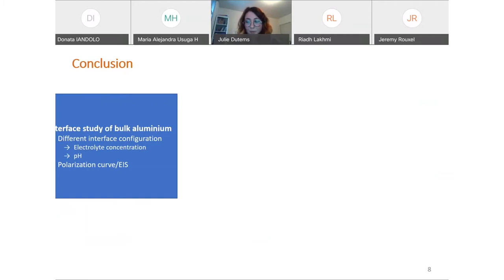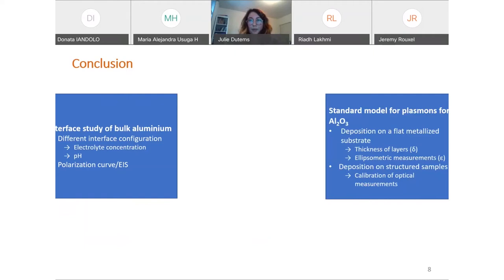At the same time, we will create a standard model for plasmon for aluminium oxide, by depositing different thicknesses of aluminium oxide on a flat metallized substrate and doing some ellipsometric measurements in order to know more about the pure oxide layer. And then deposit the same layer on our structured sample in order to create a calibration